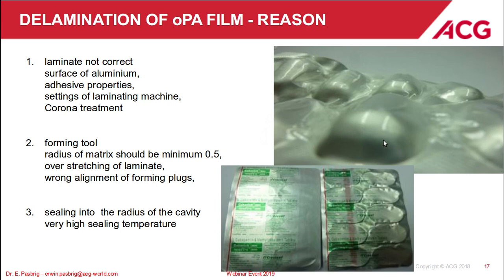On this slide, you see two photos with pictures of cold form material with delamination. The first one on the right top, you see it's totally delaminated. Such a material definitely no one would like to have. Even if it's totally delaminated, the stability of the material, as long as for sure the lid foil is not influenced, will stay. There's no influence on the stability of your packed product, because delamination is happening after forming and sealing.